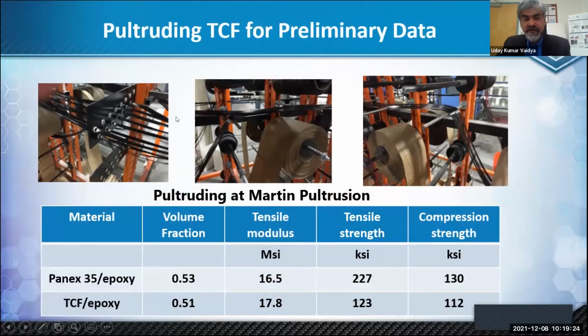Initially, the trials were held at Martin Pultrusion with the challenges of dealing with the spooling and brown paper wrapping. Despite that, I'm showing you some comparison of Panex pultruded versus TCF epoxy pultruded. You can see that the modulus is very comparable between the two. Obviously, there's a knockdown in strength, more in the tension strength than the compression strength. But these kinds of studies have to be expanded quite a bit to compare the two together.